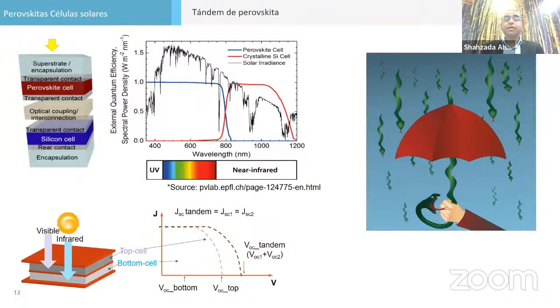Another thing is that perovskite absorbs very well in the visible part of the spectrum, and silicon absorbs from the NIR region. So it also gives us an opportunity to make tandem devices. Tandem devices, which I just commented about, have shown almost 30% power conversion efficiency, so much higher than silicon. Silicon is 26.5 now.